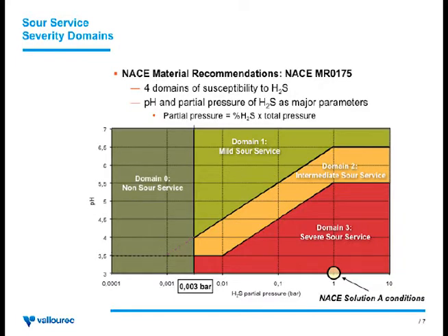The NACE Material Recommendation 0175 or the ISO 15156 is another standard that is very used in the industry as far as sour service. It is not directly applicable to drill pipe because in that norm they are considered to be used in a controlled environment, which is the mud. It's a standard that is used for other tubulars. Nevertheless, the interesting part of it is that it helps to segment the susceptibility of steel tubulars to H2S depending on the partial pressure of H2S and the pH.